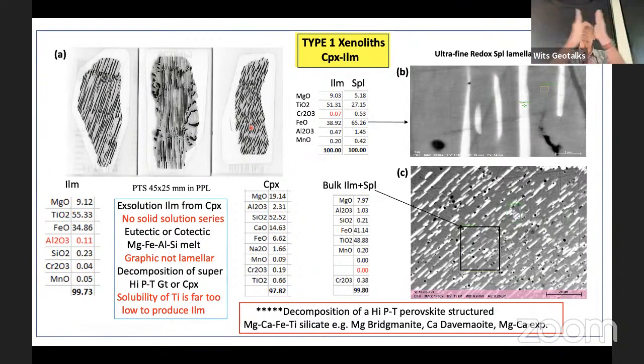In order for a solid solution to be accomplished, they have to have the same crystal structure. Now, as not a scholar, but someone who's interested in the English language, I use the word same, not similar. The same crystal structure. You can't get further away from ilmenite, which is rhombohedral, to clinopyroxene, that is either orthorhombic or monoclinic. That's as far as you can get. Secondly, the one as you see is perfectly opaque, and the other is perfectly translucent. Very different. So the question is, how did these form?